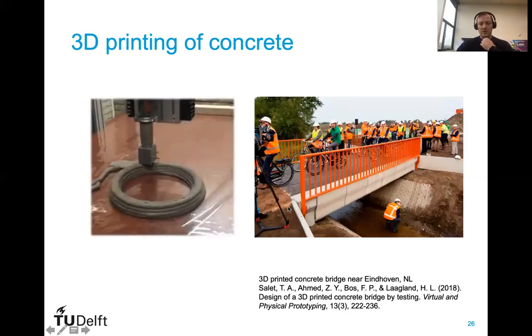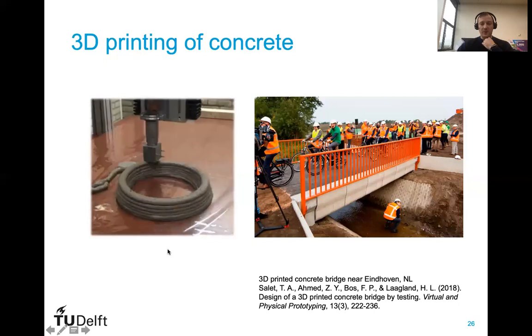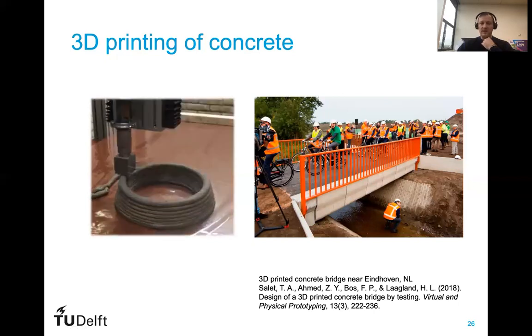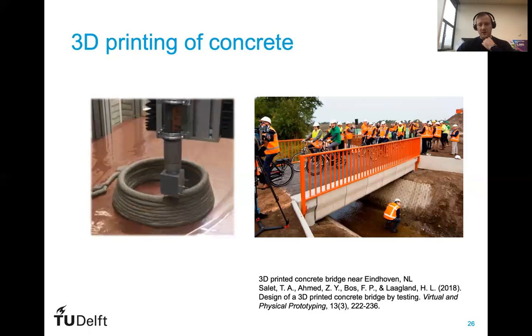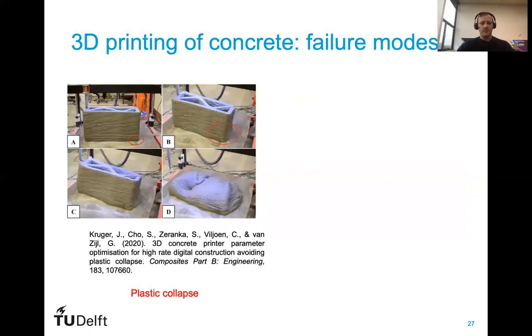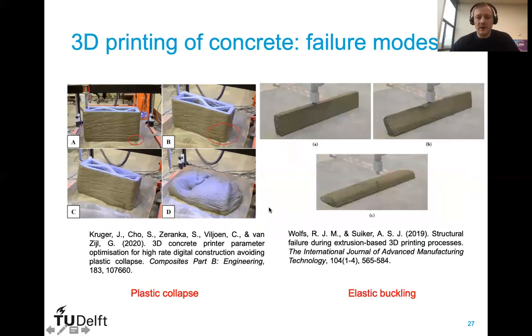So you see already some structures have been built using this technique. So it's not only a lab-based technique, there's really a lot of interest from the academia, but also from the industry in this. So if you look at 3D printing of concrete, there are two basic failure modes. Plastic collapse, where usually a bottom layer of the printing structure cannot sustain the weight of the layers on top of it, and then the structure collapses. And elastic buckling, where there is a loss of stability inside of the print during the printing process, either due to imperfections or due to geometry.